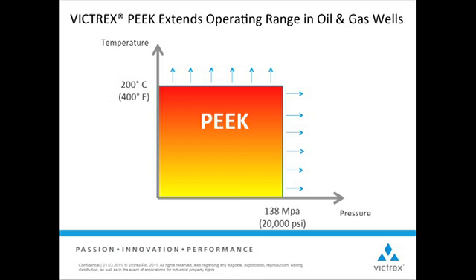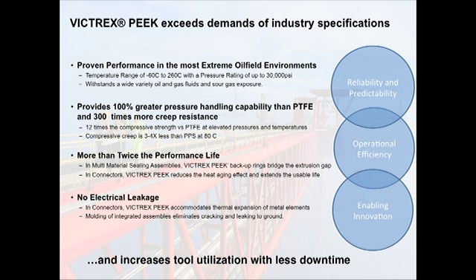New temperature and pressure targets are being defined and are driving new polymer development. Second, PEEK is known to perform well with continuous operation in this range, but can also handle limited durations at higher temperatures or pressures. So the trends and challenges for oil and gas clearly show a growing demand for extreme sealing solutions. However, I would like to take a moment to show the value that has already been delivered with VICTREX PEEK. Proven performance in the most extreme oil field environments.